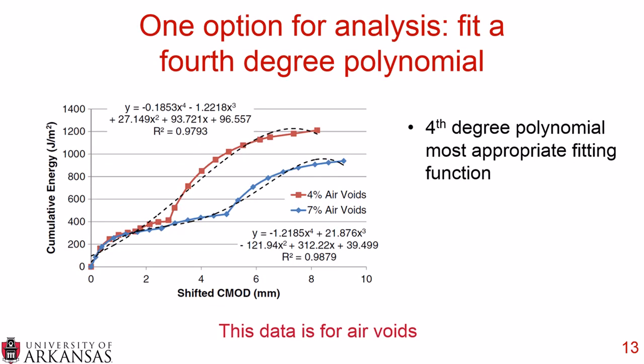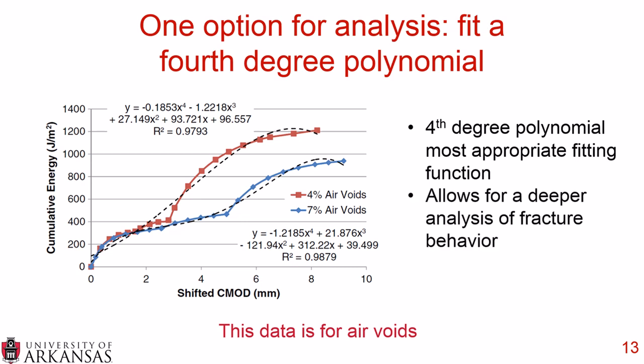You can see here just two sets of master fracture curves, one with 4% air voids, one with 7% air voids, and everything else identical with the mixtures. And we fit a fourth degree polynomial. We found that was the most appropriate fitting function. And we felt that by using these master fracture curves, we were able to allow for a deeper analysis of fracture behavior. So here on the axes, we have the cumulative energy and we have the shifted CMOD on the